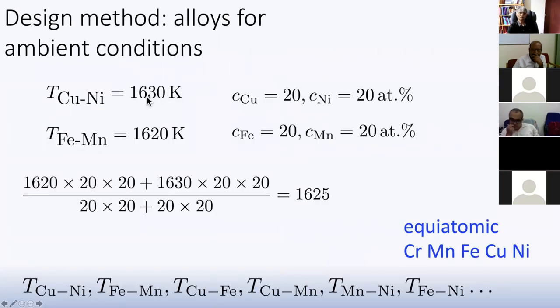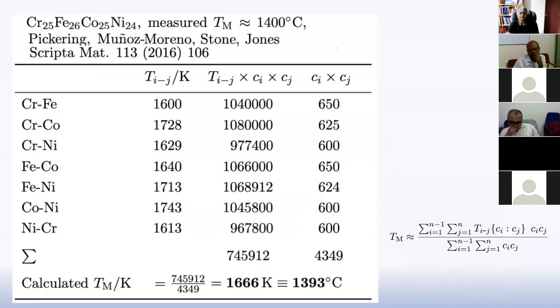Okay, so here I've got the two melting temperatures, and these are the actual concentrations. So that complicated equation that you saw earlier is simply: I take the 1620, multiply by the concentrations of iron and manganese, add the melting temperature of copper nickel multiplied by the concentrations of copper and nickel, and then divide by the sum of the products of these two, and I get an overall melting temperature of 1625. But I have to do this for all possible combinations of the binaries like copper nickel, iron manganese, and so on and so on. So I went through the process, and these are all the different combinations.